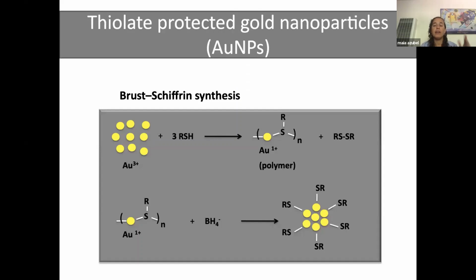So I'm a new postdoc in the lab, and let me just go one step back and mention a brief comment about how you synthesize these particles. So you have a salt of gold, you have a thiol, and I have to correct a little bit from the introduction, and you will see in a second, my passion is for the 3-MBA and not the PMBA, and I will explain why. But essentially, most of the thiols will work. In the first step of this synthesis, you form a polymer, and then you take your polymer, you add sodium borohydride, and you get your cluster.